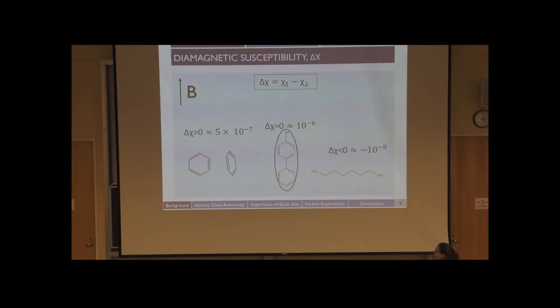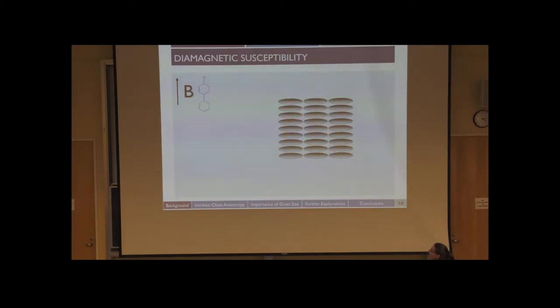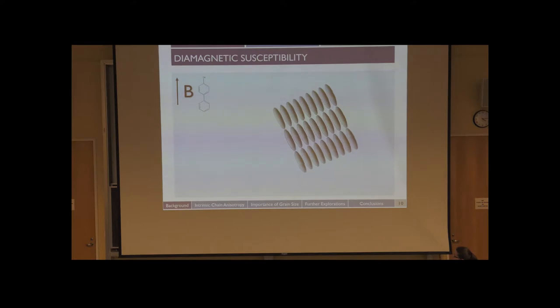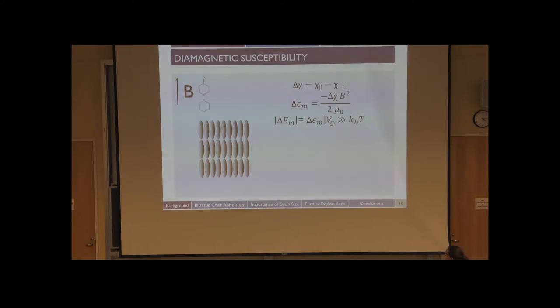If we take one of these molecules and place it in an accessible magnetic field, we find the molecule never reaches its preferred orientation — but if we have a collection of these molecules with their long axes all facing the same direction, we are able to align them in their preferred orientation. The thermodynamic driving force for alignment is a function of delta chi and field strength squared, divided by a permeability constant. The magnetostatic energy acting on an object — that quantity multiplied by the volume — must be sufficiently larger than thermal energy for alignment to take place. So we need some combination of large magnetic susceptibility, large grains or volumes, or large field strength.